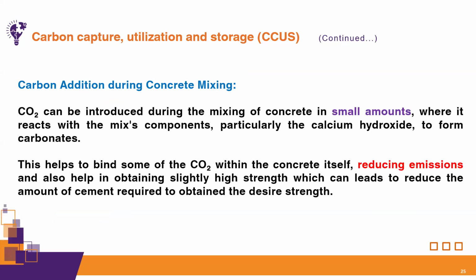So now another way of utilizing carbon in the concrete is by adding carbon into the concrete mix during the mixing phase. So carbon dioxide can be introduced during the mixing of the concrete in small amounts. The amount is very small, 0.2 to 0.5%. It depends on the type of the concrete.